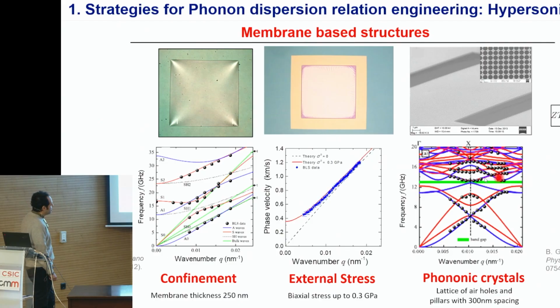So with all these 3 methods, actually we can modify the phonon dispersion relation in our materials, we can create phonon band gaps, and we can really decrease the thermal conductivity. And I will show you later on how we can also control the heat flux in these materials by creating this kind of phononic crystals.